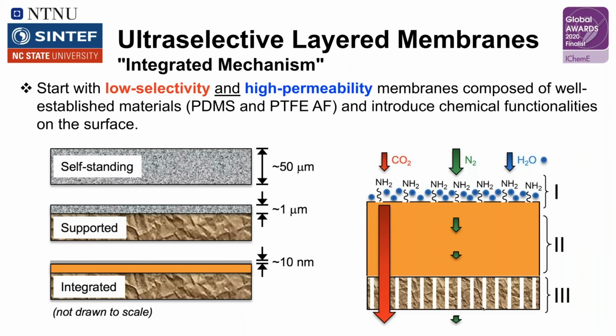The second strategy is looking at integrating membranes into a layered system. So the difference here is that we start with low selectivity but high permeability membranes, and these membranes can use some very well-established materials like polydimethylsiloxane and polytetrafluoroethylene in the amorphous form. So this is essentially Teflon, but it's amorphous Teflon. And that allows us to obtain very high permeabilities but low selectivities.